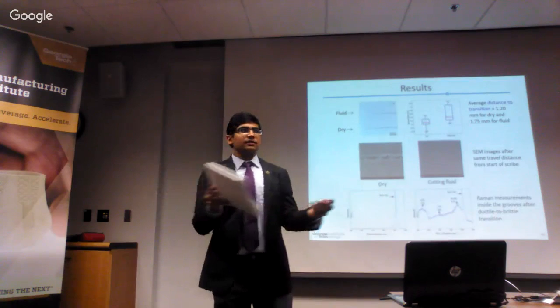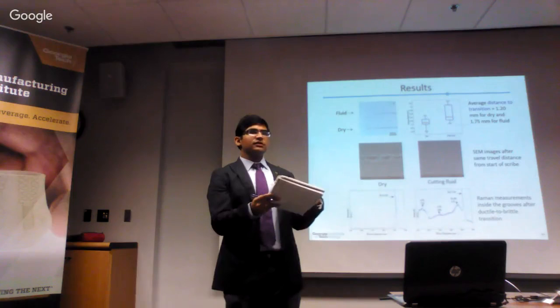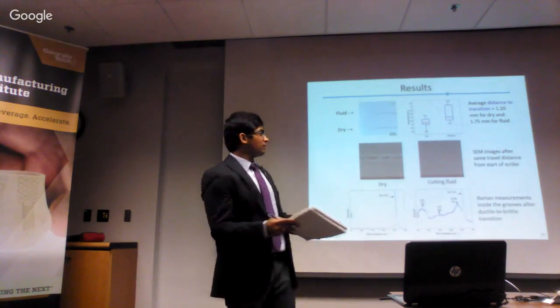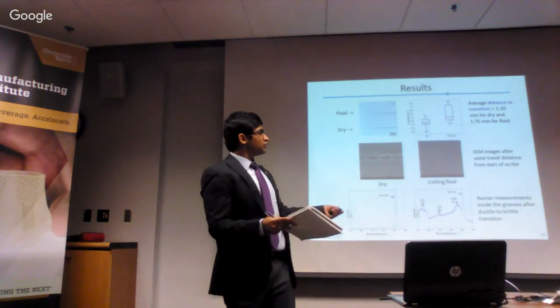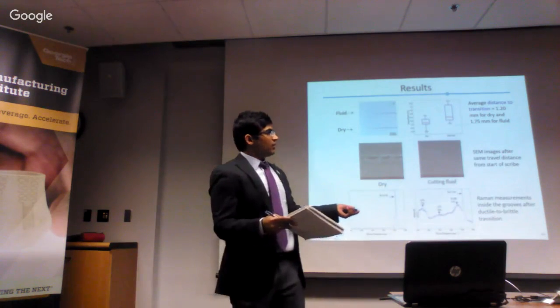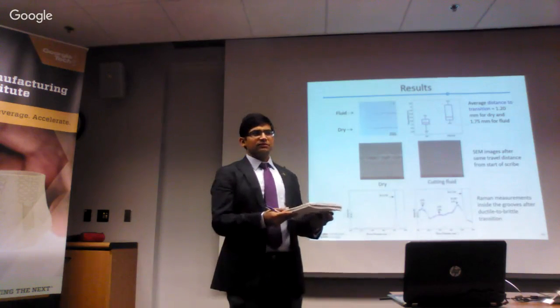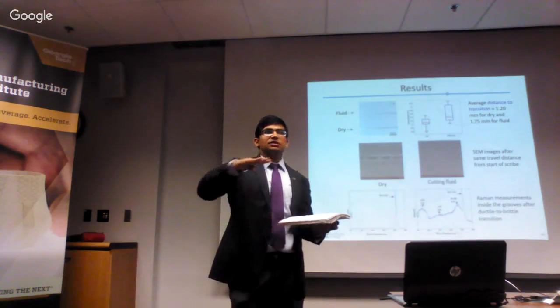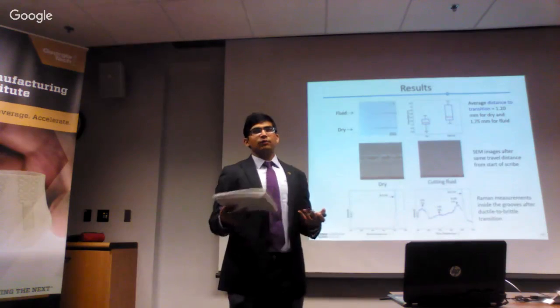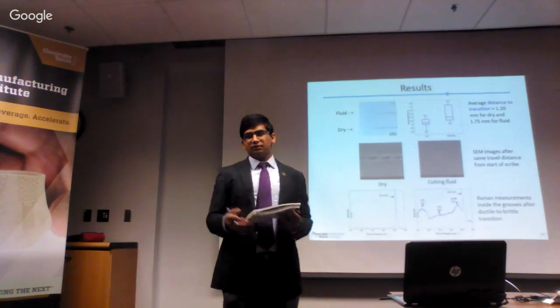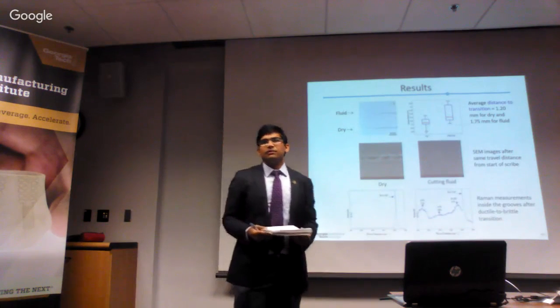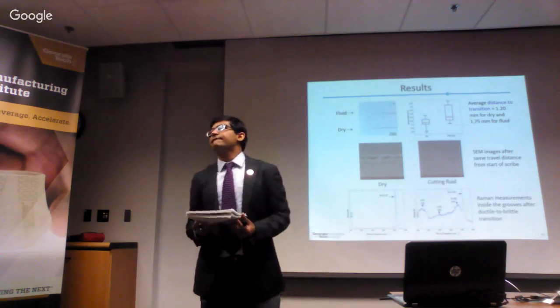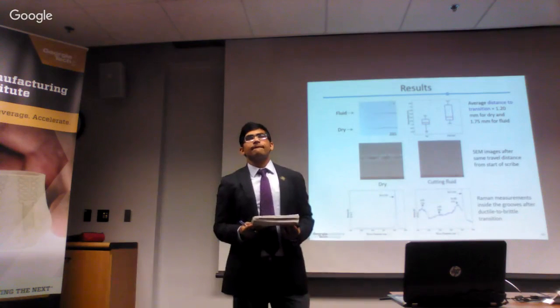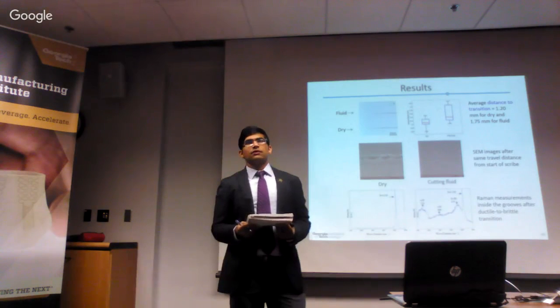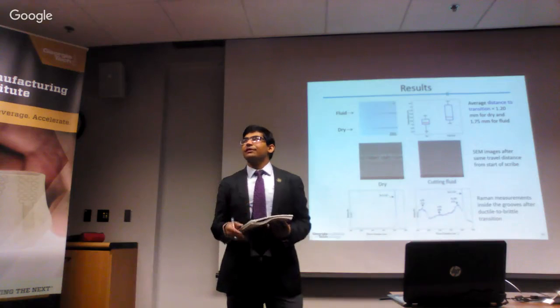So I understand the debate, but what Dr. Danlup pointed out was we are surely seeing softening, either from the hardness measurement, or from the surface morphology, or from the Raman spectroscopy, because this is showing that it is ductile. Now, the reason could be, as you're saying, whether dislocations are moving because of the electrostatic or the zeta potential creating some change in the surface charges. That is one way of explaining, by the Rehbinder and Westwood effects. But you cannot verify, I have not verified the fact that somehow there is greater mobility of dislocations in the presence of the fluid. That's what it would take to verify greater mobility of dislocations in silicon under loading. That's the difference between what Dr. Danlup is saying. You have loading, I've loaded. At pure room temperature you won't, but under load, yeah.